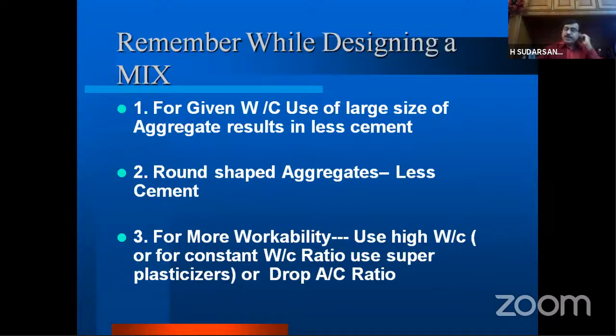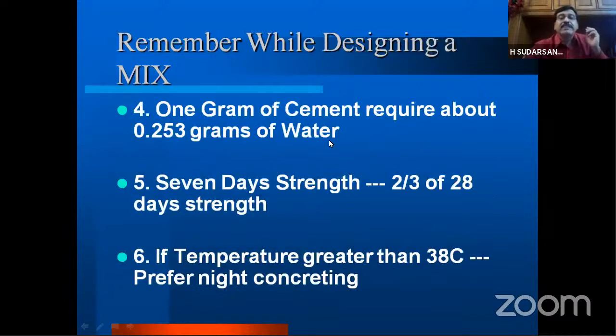Whatever method you are using for mix design, you have to remember that for a given water cement ratio, use of large size of aggregate results in less cement. Round shaped aggregates also give less cement. For more workability, use a higher water cement ratio, or for constant water cement ratio, use superplasticizers and drop the aggregate cement ratio. One gram of cement requires about 0.253 grams of water. This is a very useful thumb rule. And 7-day strength is about 2/3 of the normal 28-day strength.